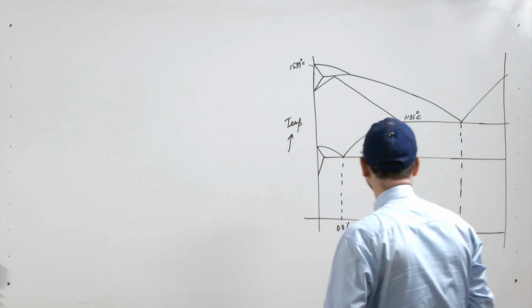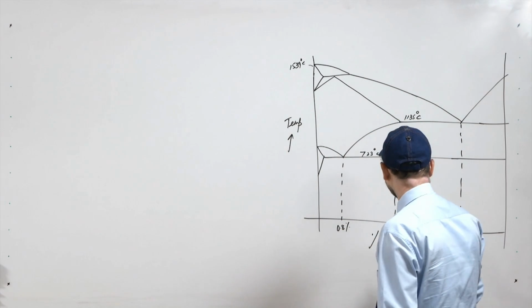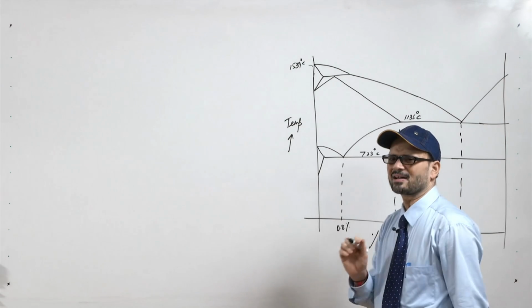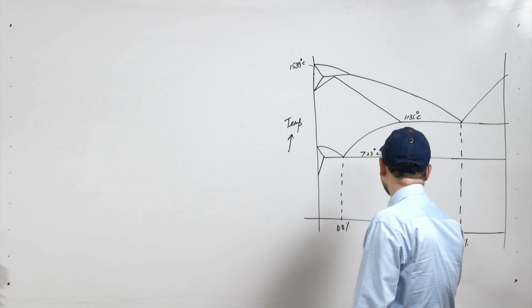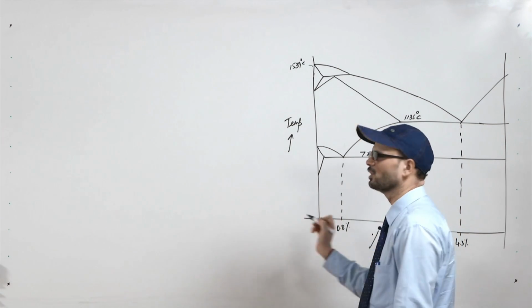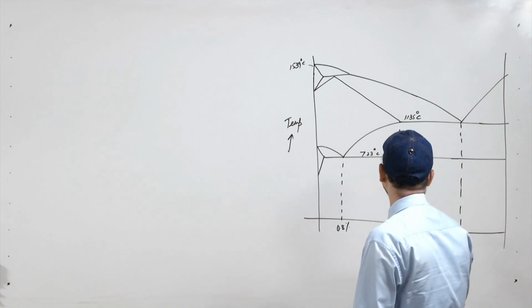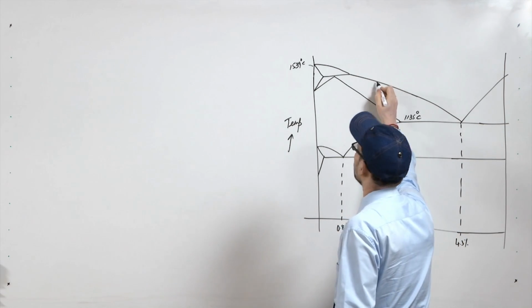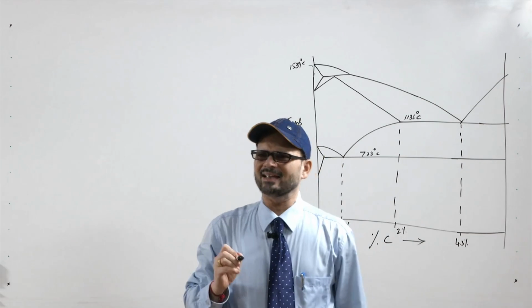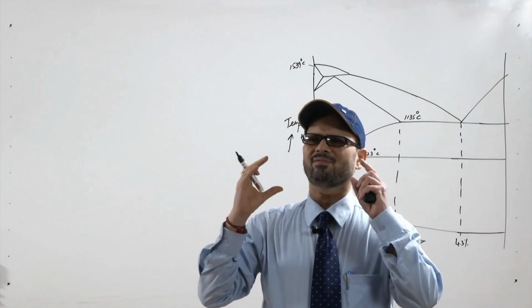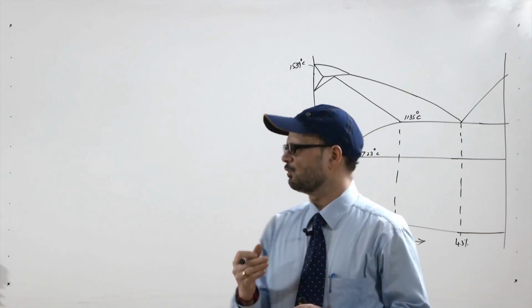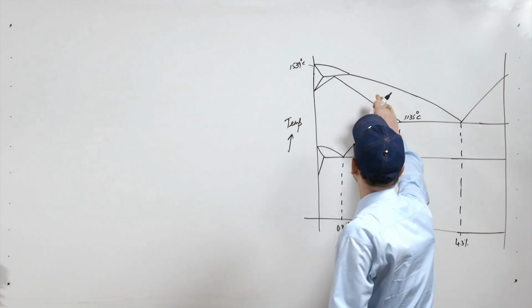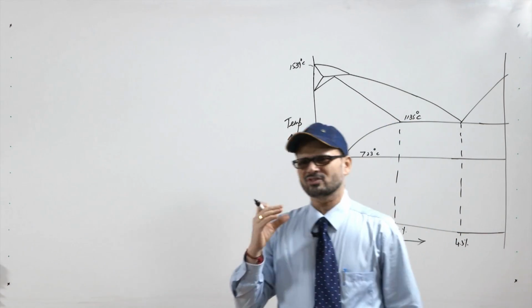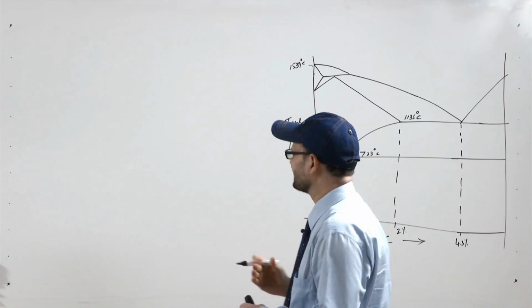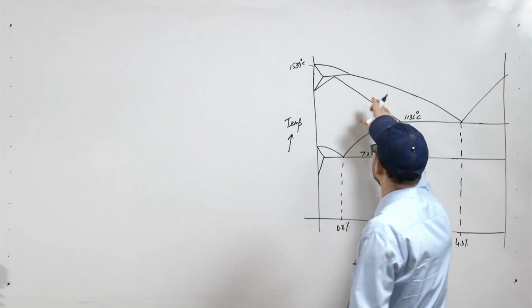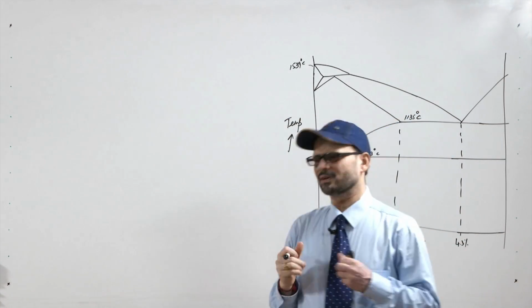However, steel is normally an iron carbon alloy with some alloying elements, but with carbon below 2% or 1.5%, and in this range the temperature is quite high. So, you require a furnace that can generate high temperature to melt the material. In that case the furnace requirement has to be different, and the lining requirement has to be different.